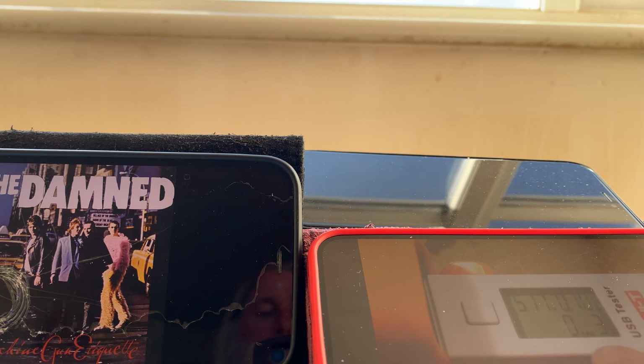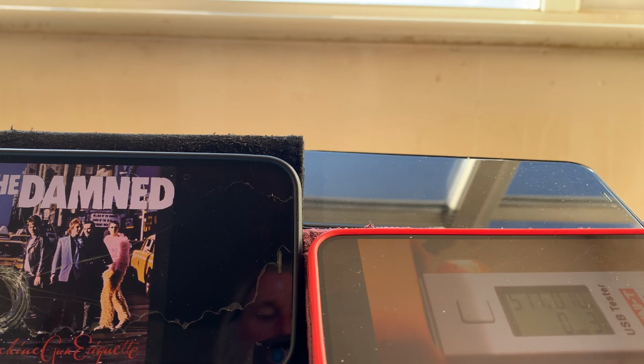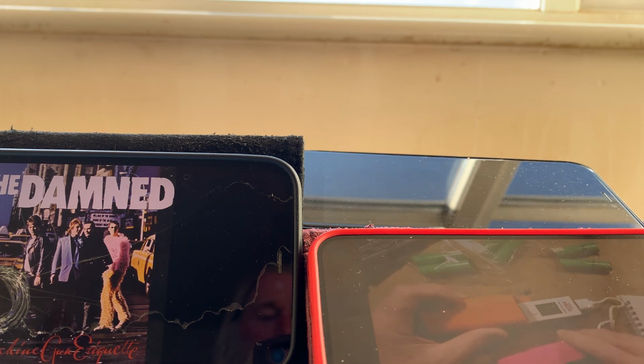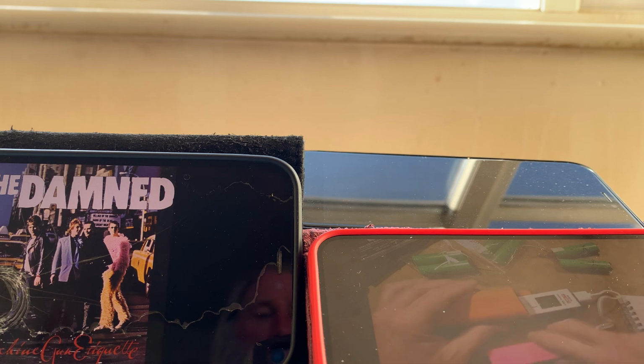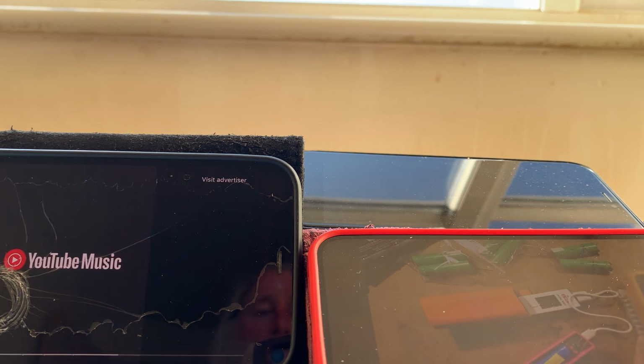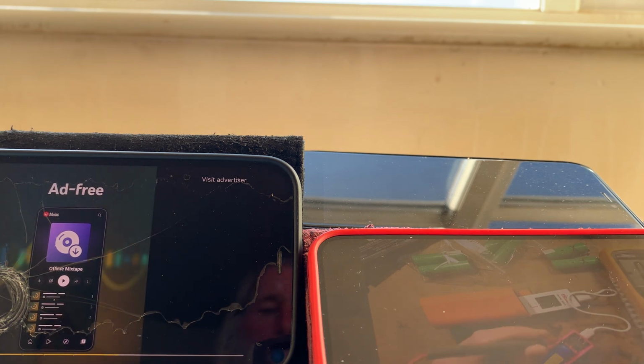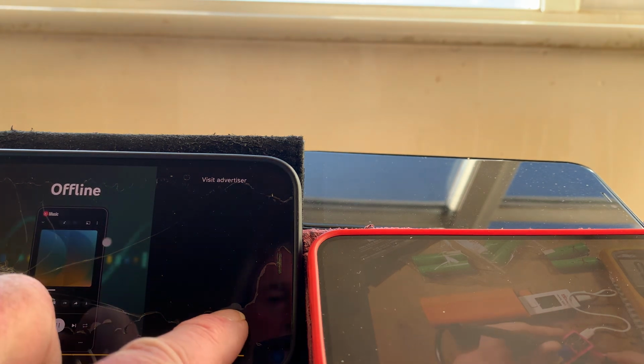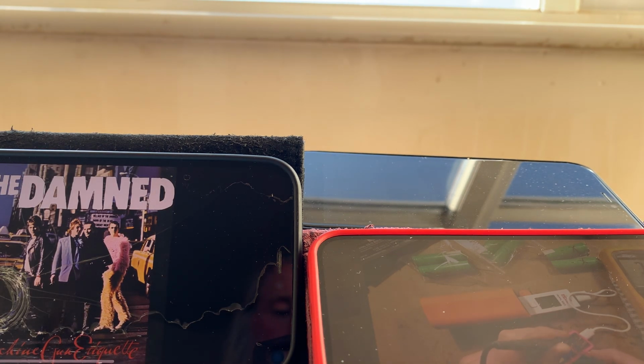So it's trickle charging at about 100 milliamps, and as soon as the voltage in the cell reaches about 2.5 to 3 volts, which is considered acceptable, it will then kick into full charge mode, and the current will suddenly go up to about 500 milliamps. Oh, it's better. It's just gone up to 1 amp. Let's measure the voltage. Where's the meter? What voltage did it deem was acceptable? Yep, the LED started flashing now because it's quite happy to charge it at that. As soon as it's gone above about 3 volts, it's deemed that it's at a level that it can charge properly at the full current. That's good to know.